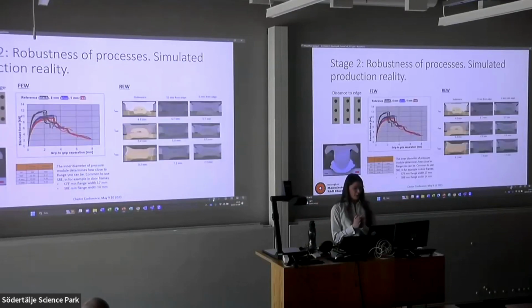Yes, and then I move on to the robustness of the process. So here we had quite a lot of different factors, and I'm not sure I will be able to go through them all, but we tried varying distance to edge, for example. And the main thing to take with us from here is that the inner diameter of the pressure module for friction element welding determines how close to the flange you can be. So when you have very narrow flanges in, for example, door frames, it is common to use this smaller SRE element.